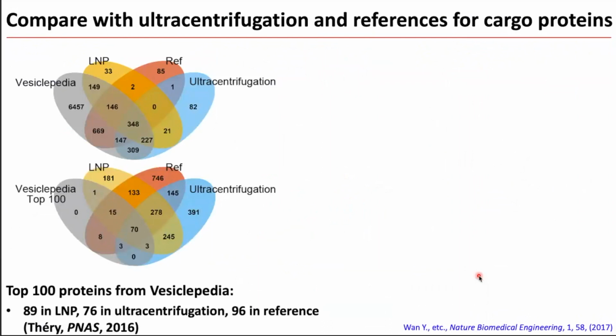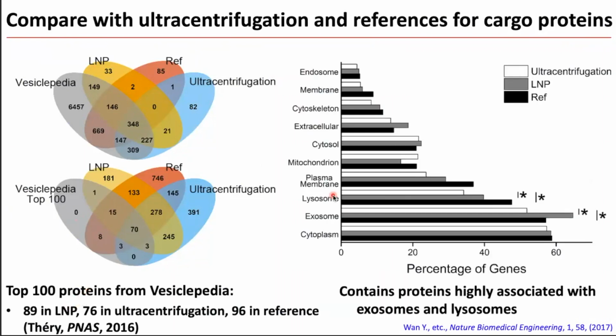In particular, we also run some proteomics study to compare our method with ultracentrifugation and also a reference paper published by Théry group in PNAS in 2016. So what we see is, of the top 100 proteins from Vesiclepedia, we can find about 89 of those proteins using our lipid nanoprobe isolation approach, compared with about 76 using ultracentrifugation and 96 in the reference paper. We also did a little bit further study showing that the proteins from the proteomics study are highly associated with exosomes and lysosome fraction, if we just characterize these proteins according to their cellular locations.